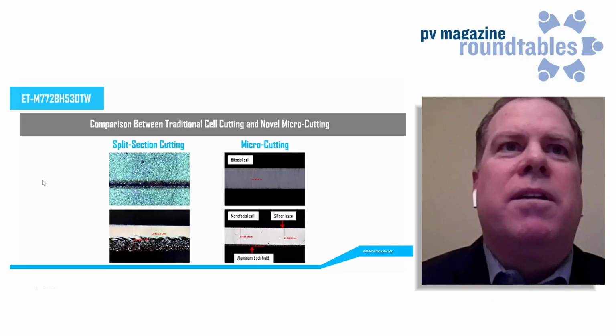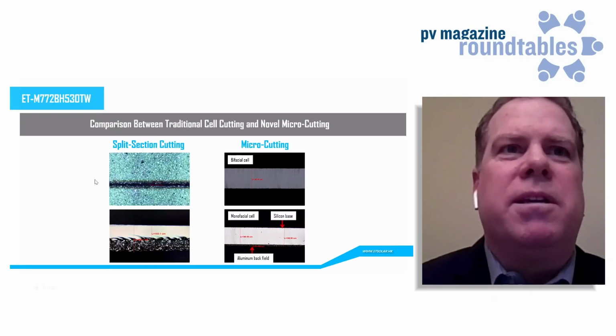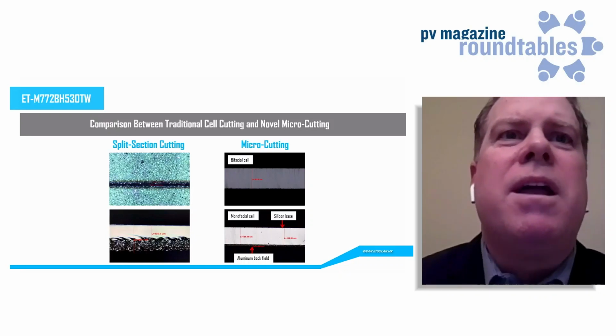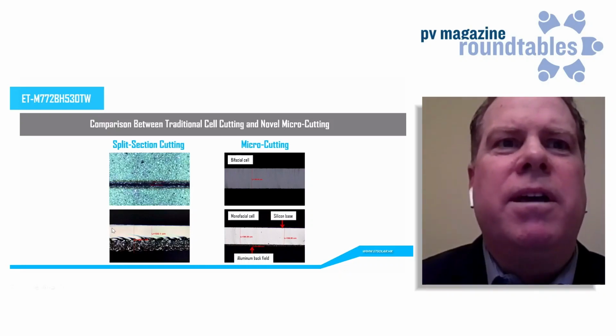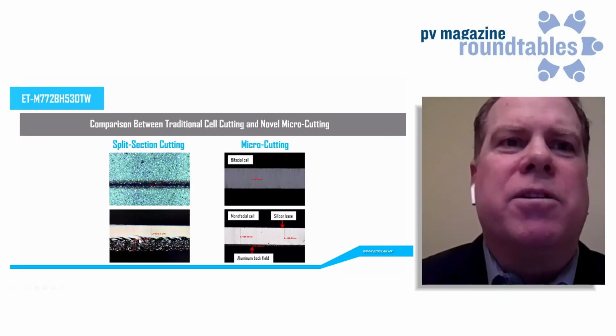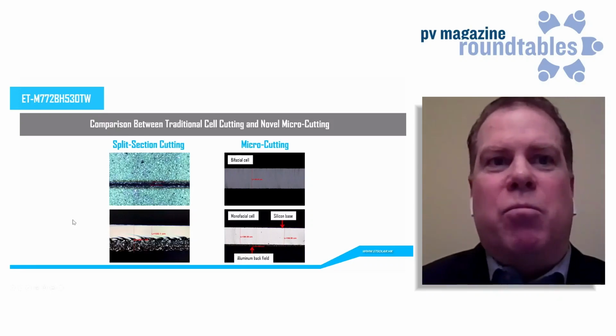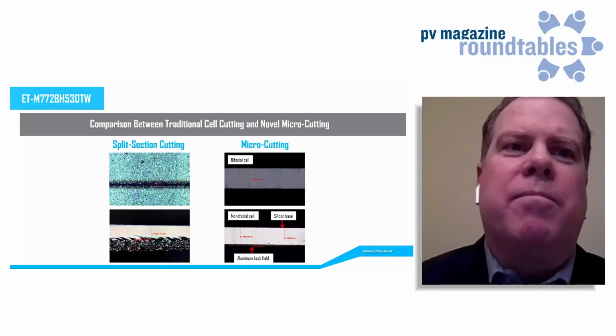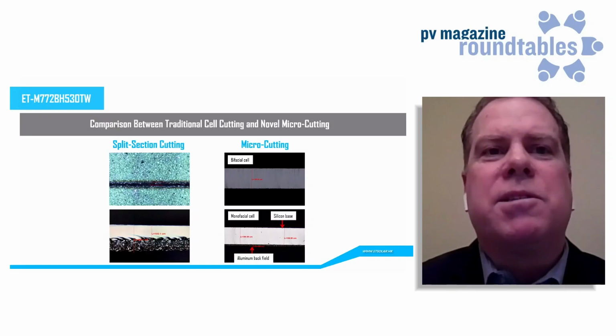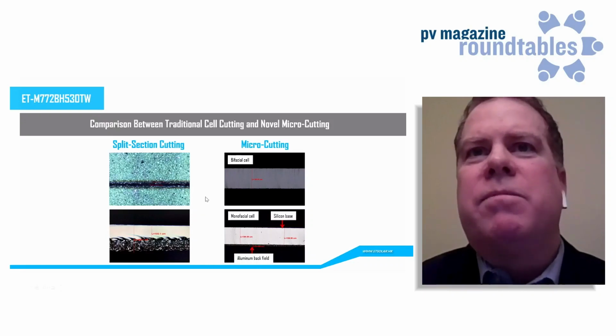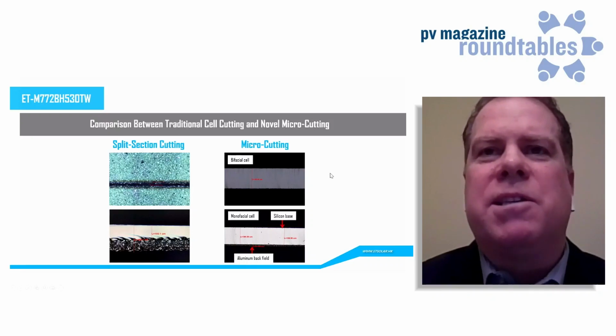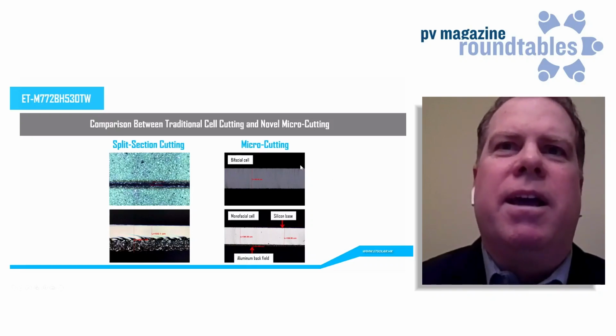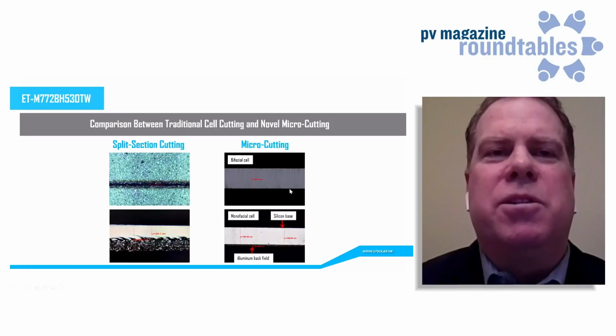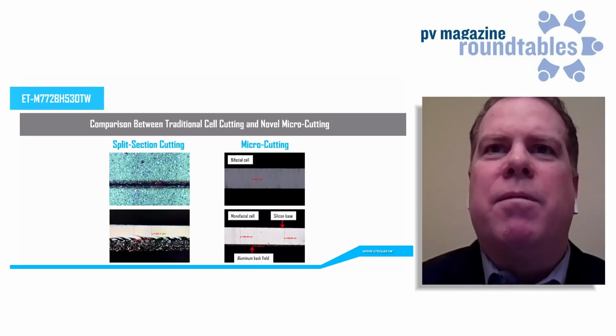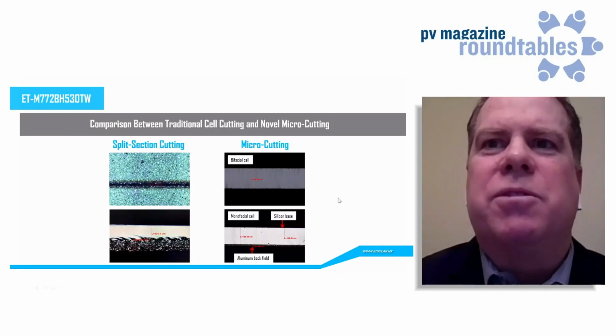So you can see on the left, there's a split section of the cutting. You can see the damages from the high power laser and how that affects the material. And then even a closer up perspective of that, you can see these fragments that are along the surface causing some weakness to the material, and that would potentially lead to further microcracks within the material. And on the right, we have the microcutting approach, and you can see the vast difference of that clean line that's created and no thermal damage done to the cell substrate itself. We've done this both on the bifacial and monofacial cell.